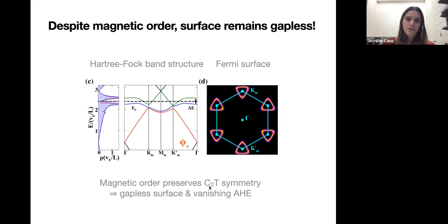One way that you could get a Hall effect is by breaking this C2T symmetry. And in fact, the surface of bismuth selenide and bismuth telluride has this only as an approximate symmetry. It's not exact, because those surfaces don't have a pi rotation. They have threefold symmetry, but not sixfold. So for those particular materials which don't have this symmetry, it's symmetry allowed, there could be an anomalous Hall term. And it remains to compute what the magnitude of that term would be.